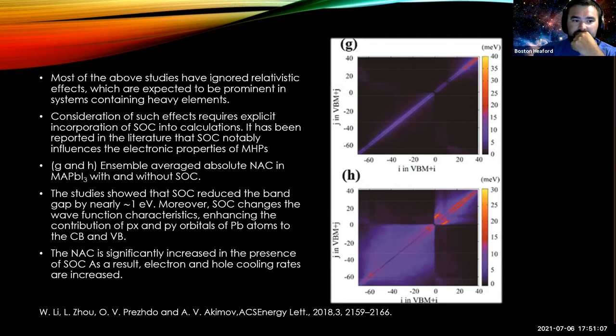And so for example, on the right here, we have the averaged absolute nonadiabatic coupling in the methyl ammonium perovskite with and without spin orbit coupling. These studies showed that the spin orbit coupling reduced the band gap by nearly one electron volt. Moreover, the spin orbit coupling changes the wave function characteristics, enhancing the contribution of the px and py orbitals of the lead atoms to the conduction band and valence band. And the nonadiabatic coupling is significantly increased in the presence of the spin orbit coupling.